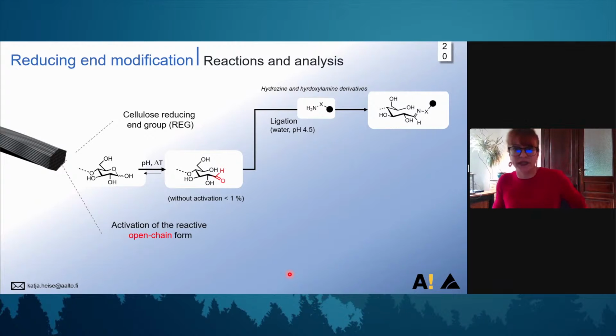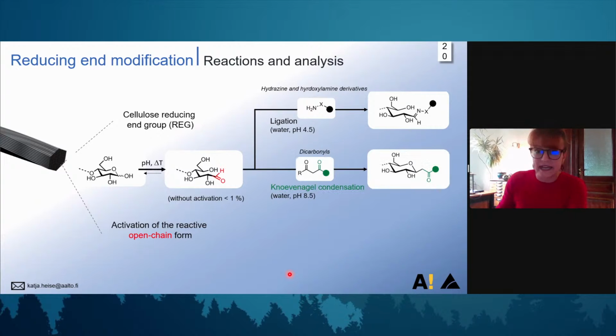This has been done with hydrazines or hydrazine derivatives and hydroxylamine derivatives. What you obtain are hydrazones and oximes. The reactions are carried out in water at acidic pH, and they work really nicely. A second possibility, known from monosaccharide or disaccharide chemistry, is the use of dicarbonyl compounds in the so-called Knoevenagel condensation. And what you obtain are ketone functionalities on your reducing ends. And these reactions, I will go into a bit more detail with this one later, are carried out in water